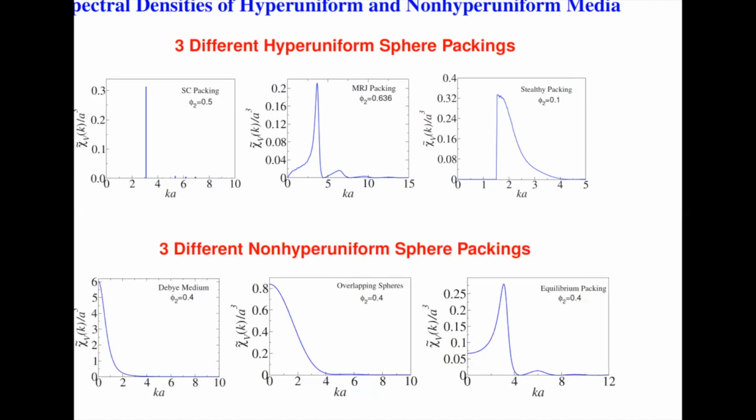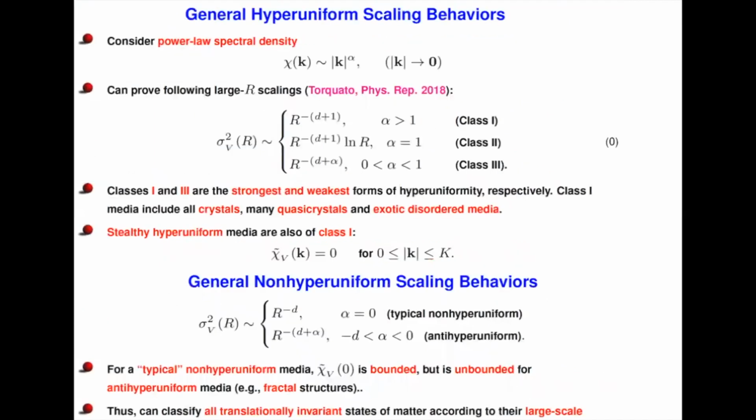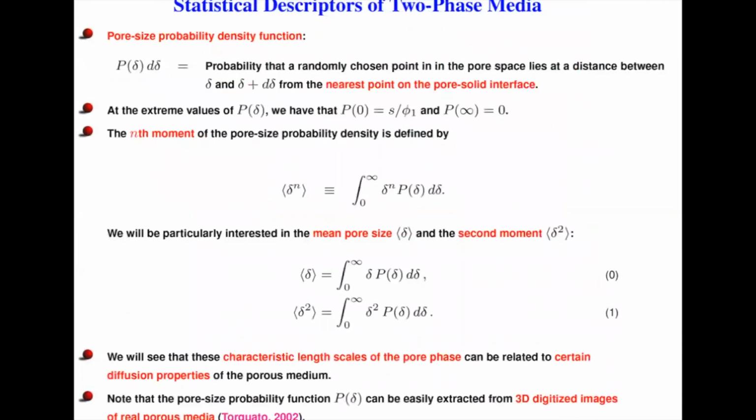Okay. I wondered about the pore size distribution. You say at the limit of delta equals 0, you get the specific surface divided by the porosity. I wonder why that is. It was that last slide you were on. Yeah, it's because I'm asking for very, very small circles. You can imagine placing down circles of a given size. And because it's a probability density, I'm thinking about a differential element around the interface. And so that's why you end up picking up the specific surface.